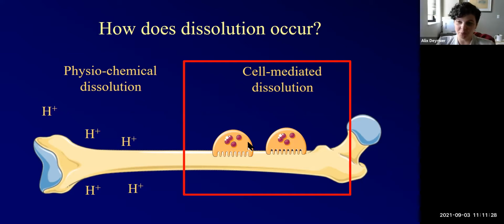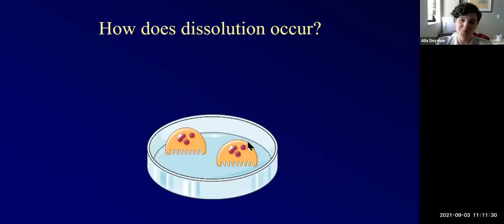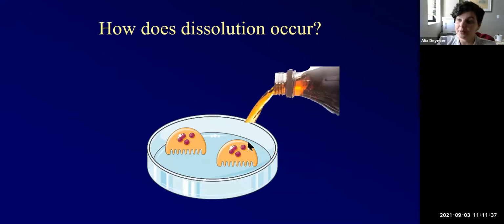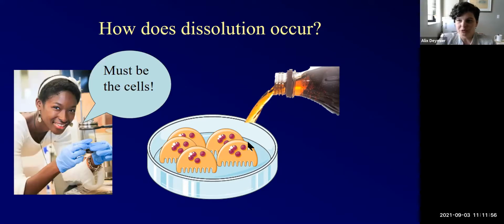And the reason they're so motivated is because they've done experiments where they take these osteoclasts, these bone-resorbing cells, and they add acid to it in a petri dish type of environment, so in vitro. And when they do that, they see that the osteoclasts replicate at higher rates and they become more active. So they said, great, if I add acid to a cell in a petri dish, it multiplies, it becomes more active. So it must be the cells. That's what's controlling the dissolution mechanism.